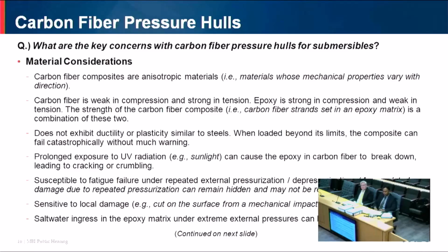Because in steel or titanium, once you reach the yield point, the material starts deforming. And then you reach the ultimate tensile strength and it deforms further and then the material fractures. So there is plastic deformation of the material from the yield point till the time it fractures. And then strain hardening of the material takes place till you reach ultimate tensile strength. And after that, there's something called necking, or the reduction in area of the material. Okay? So this effect is not seen in carbon fiber composites. They go directly to the point of failure and then suddenly fail.